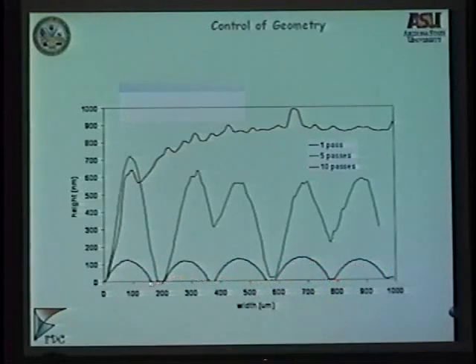So by surface tension the dots stay separated. You could adjust the chemistry again and make them overlap. So you have a bimodal distribution of P-dot. And every two dots, by adjusting the frequency of the printing, you allow them here not to overlap at all. And that you could build eventually for solar cells.